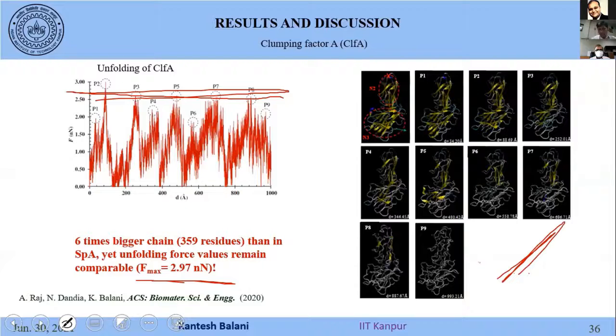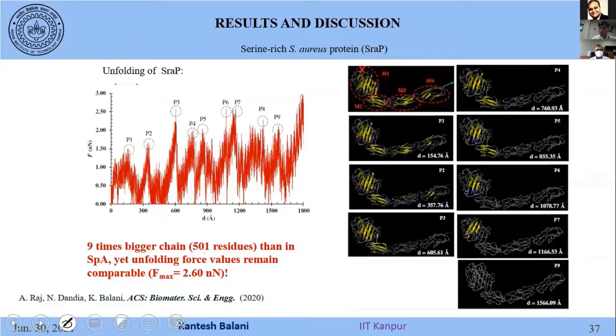So the alpha helices, beta chain, you will see that beta chain is shown by yellow region, and by the end they all are disappearing. There are alpha helices which are typically shown by blue, and they also tend to disappear later on. They are just opening up, and they are just disappearing. But the forces are still of the order of nanonewtons. And again, we took the serine-rich S. aureus protein. Here also the forces are still 2.60 nanonewton.